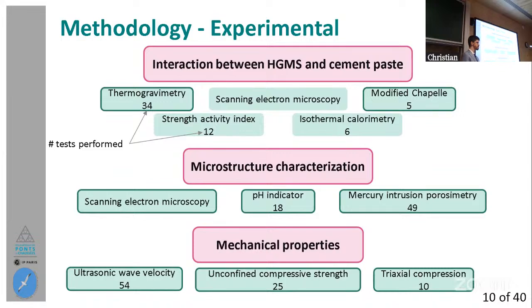In terms of pressure for the system, yes. But you can see that in an MIP test the effective stress remains almost equal to 0 because you put mercury inside and outside. But since you have some spheres, the spheres are confined by the mercury. Well, I think there is this kind of device. Yes. You can measure the diffusivity coefficient and the nitrogen adsorption.